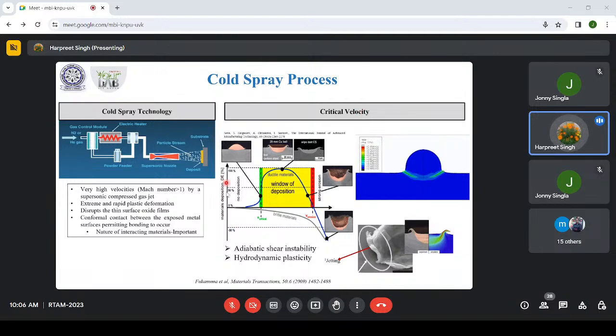You can see here we have material deposition on this axis, which is represented in terms of deposition efficiency. So what is deposition efficiency? Basically, it means that if 1 kg of powder is thrown towards the substrate, what percentage is retained as a coating, because there will be some loss of the material. So that is basically deposition efficiency. As an engineer, we will always want a high value, because we don't want to waste our powder, which is costly most of the time.